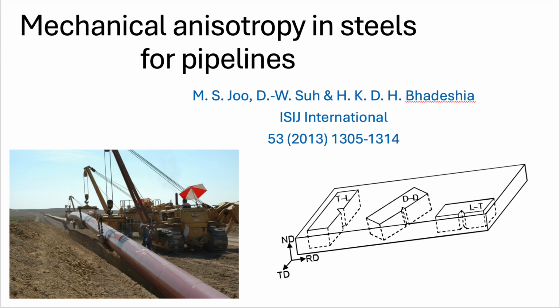Not entirely. You can also try reducing the amount of deformation during rolling, which leads to less stretching, smaller aspect ratios. But maybe the cleverest approach is chemical. Adding something else to the mix. Exactly. Adding elements like cerium or zirconium or titanium. These react with the sulfur and oxygen. They form compounds that are much harder and less deformable at rolling temperatures.